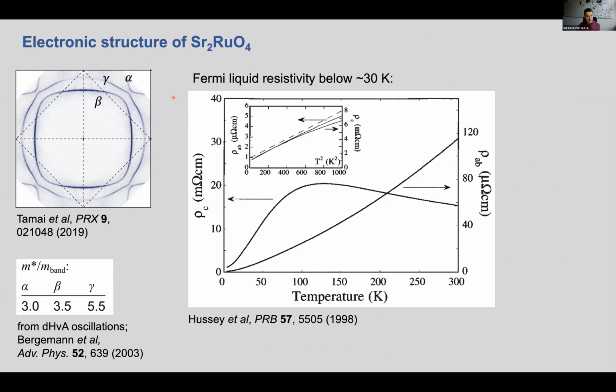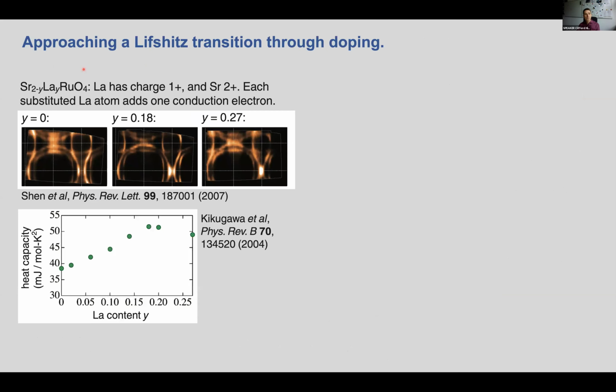The fact that the Lifshitz transition is caused by the gamma sheet under uniaxial stress, this distorts elliptically and it touches the Brillouin zone boundary at a single point. It can also be manipulated with doping. So here's some work before we started our uniaxial stress measurements.